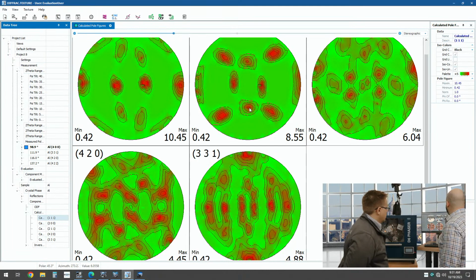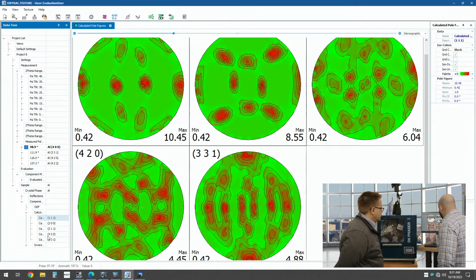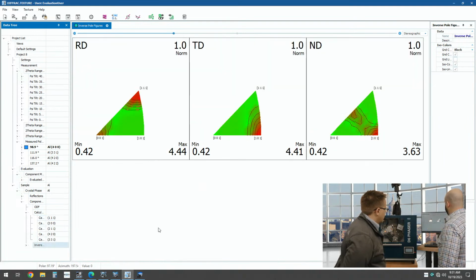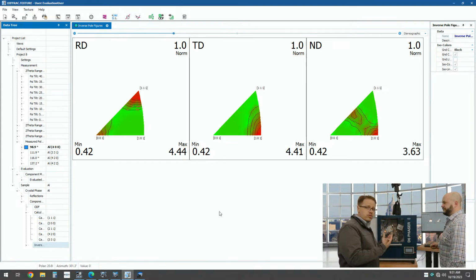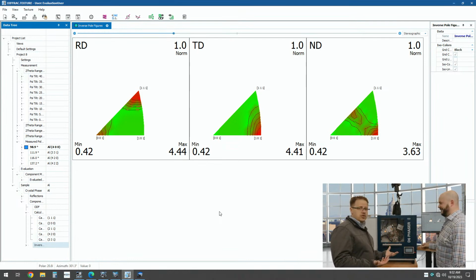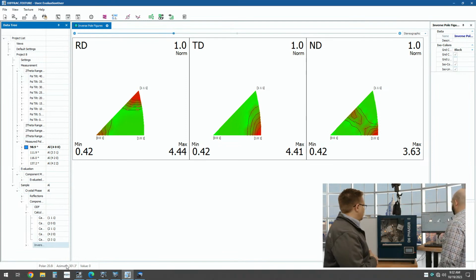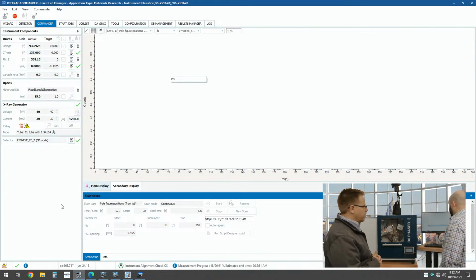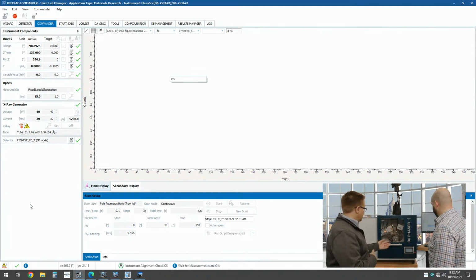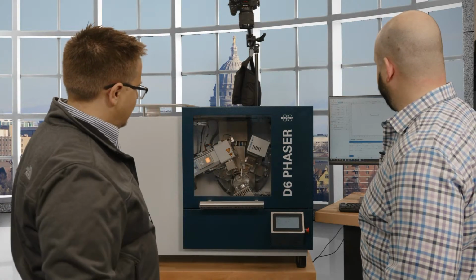So you can see where we have a higher probability of hitting a crystallite. And then if we go to a classic inverse pole figure view here, you can see in the rolling direction we have 111 texture, and the transverse 101, and then normal 101 as well. And for this type of measurement for cans, it's really important you have the right texture. Otherwise, you run into issues like earring when it's pushing the cans out. So that measurement is pretty straightforward on this instrument. And you can even see here now it's at the higher angle, so even more extreme looking.